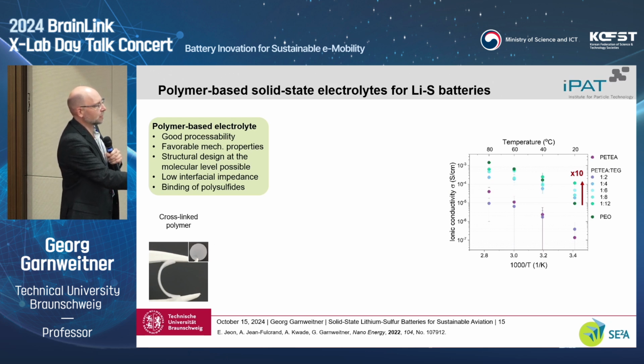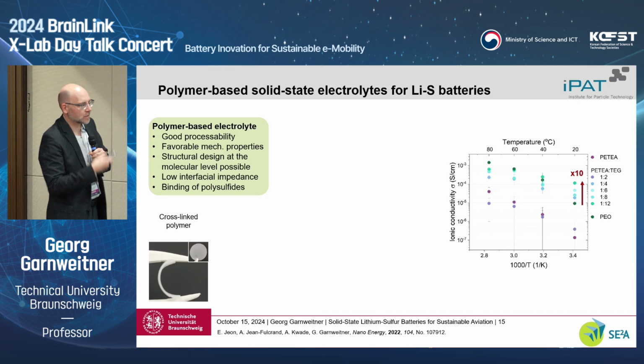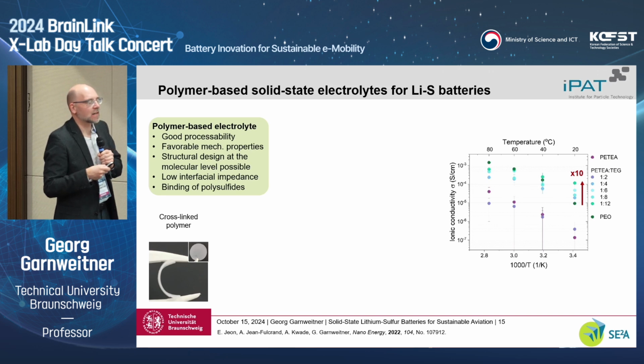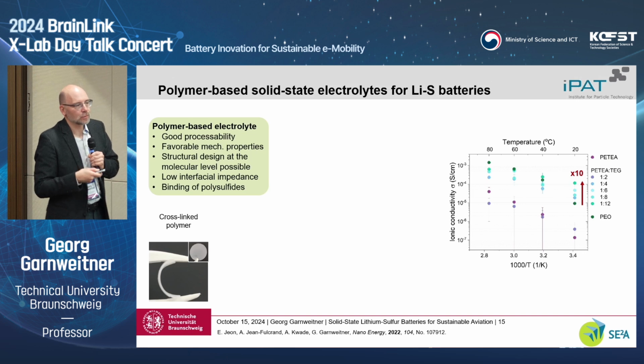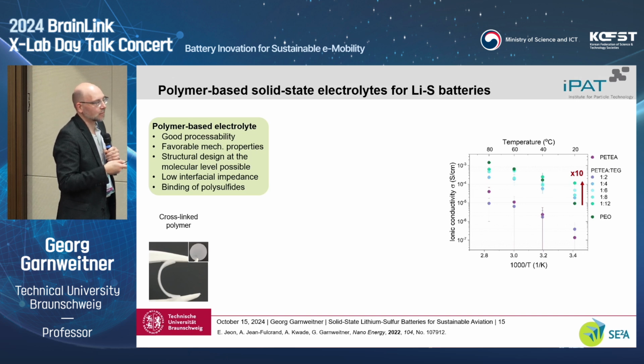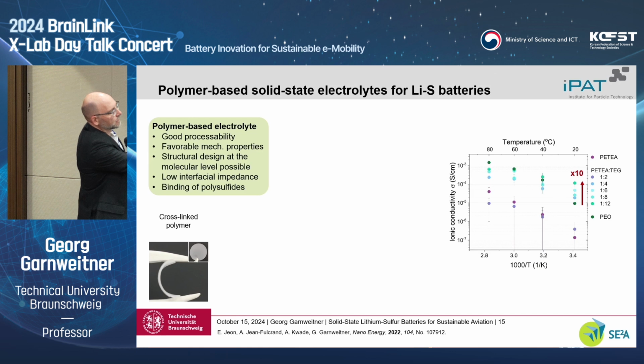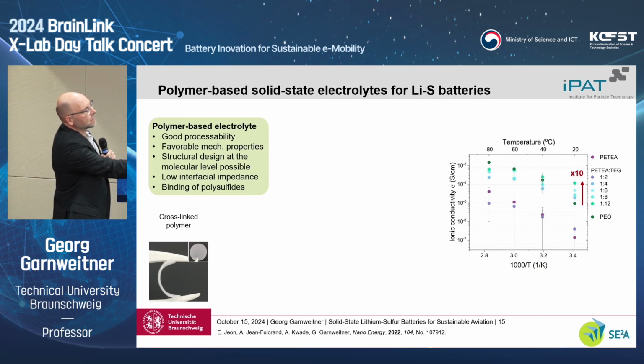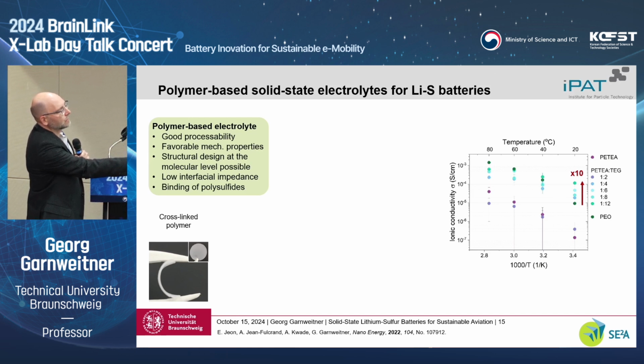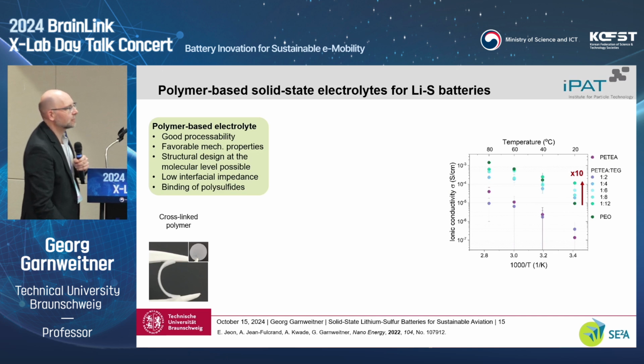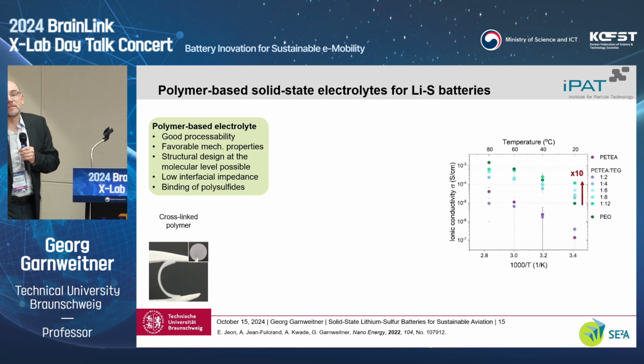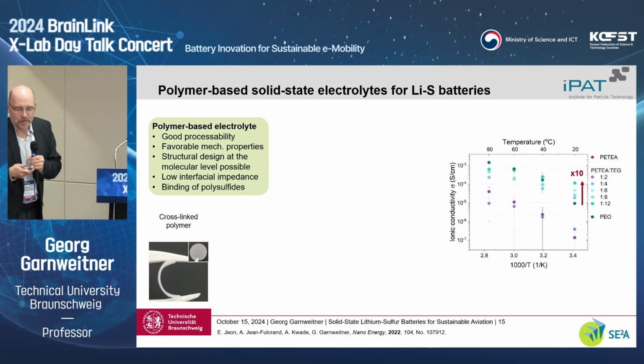And this is basically a flexible membrane formed from this polymer, which we can easily process. By optimizing the composition of that polymer, we could already see a good effect on the ionic conductivity. Here on the right-hand side, you see the PEO in the dark green points, where you see a strong temperature dependency, and at room temperature it is only low, 10 to the power of -5 Siemens per centimeter, and this means it's not sufficient for room temperature operation.